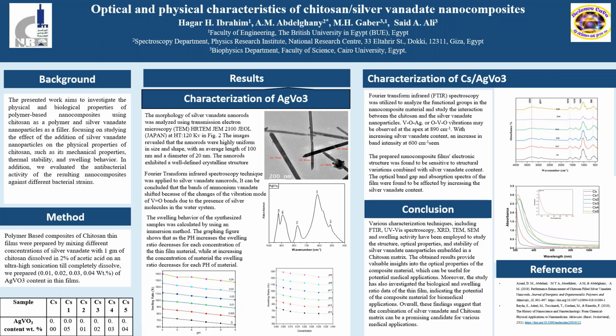The swelling behavior of the synthesized samples was calculated using an immersion method, in which a dry amount of each sample was immersed in 6 different buffer solutions. The graph shows that the swelling ratio decreases with the increase in concentration or pH of each thin film material. The obtained results provide valuable insights into the optical properties of the composite material, which can be useful for potential medical applications. They also investigated the biological and swelling ratio data of the thin film, indicating the potential of the composite material for biomedical applications. The combination of silver vanadate and chitosan matrix can be a promising candidate for various medical applications.